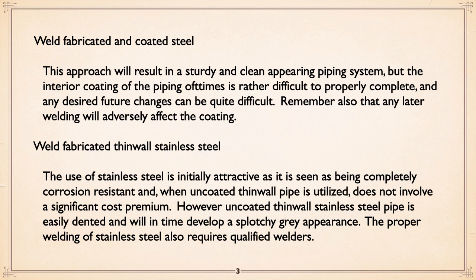Weld fabricated thin wall stainless steel. One of the approaches is, well, gee whiz, we don't have to worry about coating if we use stainless steel. It seems attractive because it's completely corrosion resistant. And if you use uncoated thin wall stainless, it really isn't much cost difference from coated regular steel pipe. However, uncoated stainless pipe is easily dented. You drop something heavy on it, it'll dent, and with time will develop a blotchy gray appearance. And the proper welding of stainless also requires qualified welders that know what they're doing with stainless.